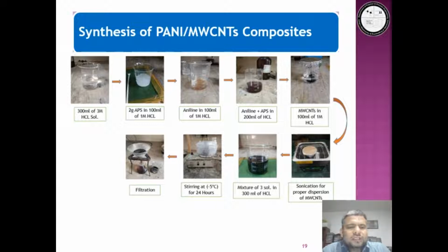Ammonium persulfate was dissolved in HCl to get a uniform solution. Secondly, the acidic solution of aniline was prepared by dissolving 5 ml of aniline in HCl. Next, the precise amount of multi-wall carbon nanotubes in a 1 molar solution of HCl was dispersed by sonication for 30 to 40 minutes. Then these three solutions were mixed and stirred for 24 hours at 0 degrees Celsius. Initially, the prepared solution was filtered, washed and dried at 40 degrees Celsius for 24 hours. The samples were prepared in a similar way, just by varying the amount of multi-wall carbon nanotubes.